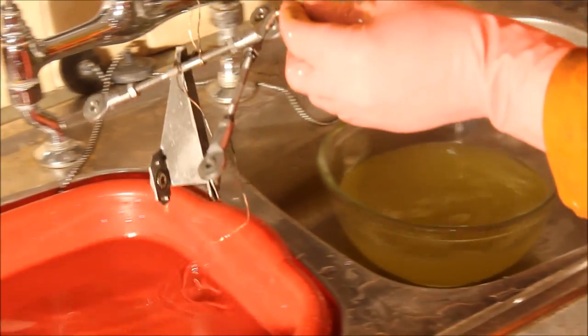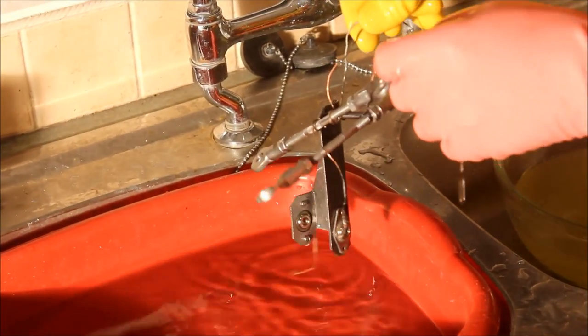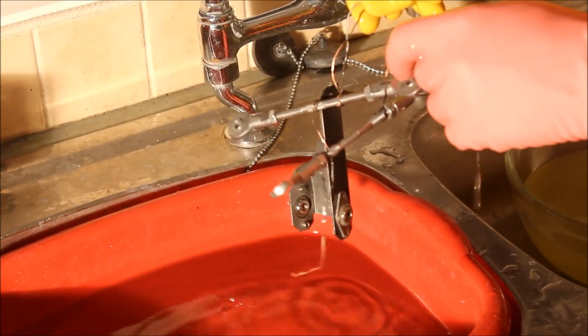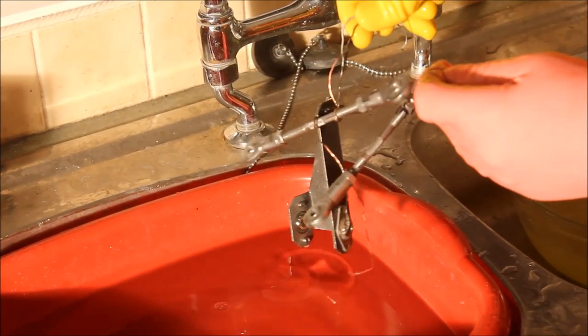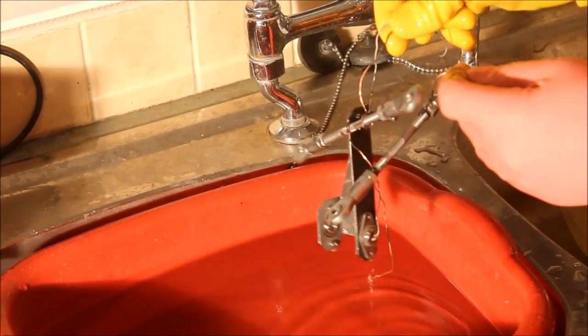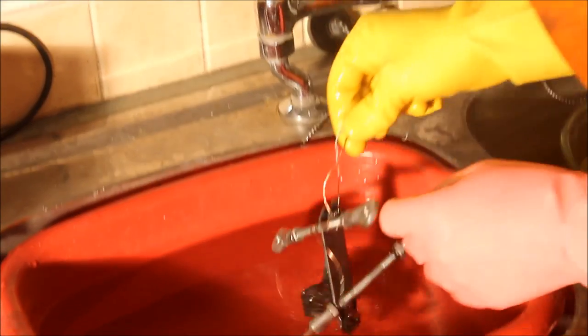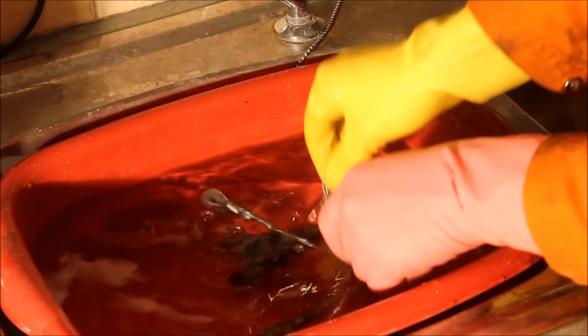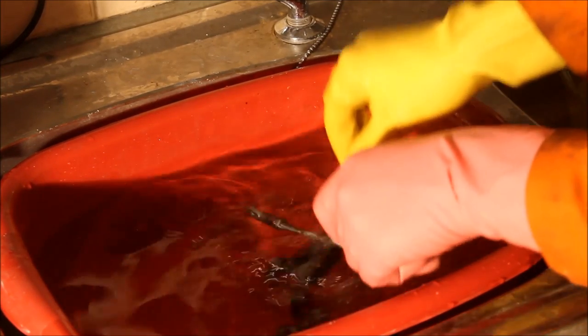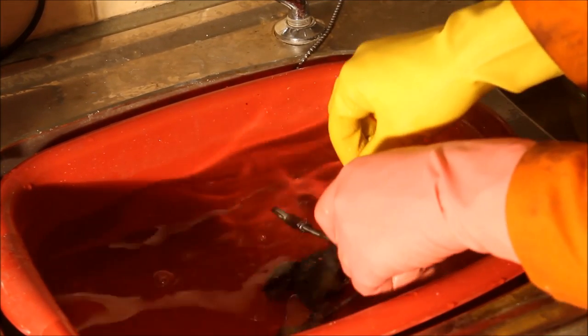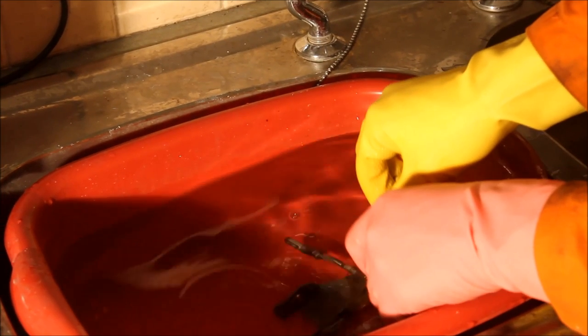Right, and when they come out of the acid bath, that's what they'll look like, absolutely pristine steel surface. Now, the surface is very much called active. It will rust within minutes if you leave it in the air. So just give them a quick rinse off in some clean water. And then we're going to put them straight into the electrolyte and start plating them.